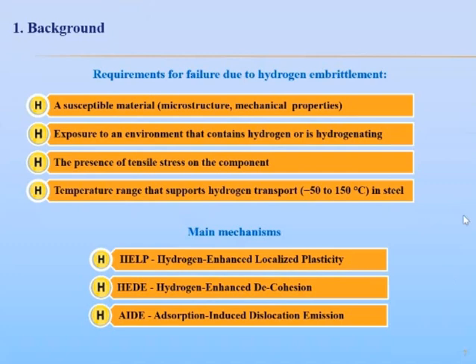And the adsorption-induced dislocation emission mechanism is based on hydrogen-induced weakening of intermetallic bonds, with crack growth occurring by localized slip. It's assumed that adsorbed hydrogen weakens substrate interatomic bonds and thereby facilitates the emission of dislocations from crack tips. There is also substantial dislocation emission ahead of the crack tip, which results in the formation of voids around particles or at slip band intersections. Such behavior means that crack propagation occurs due to dislocation emission from crack tips, also with a contribution from the void formation ahead of the crack tip.